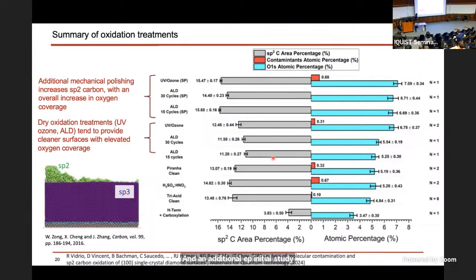And in particular, mechanical polishing, which sometimes you need to do to make your diamond smooth enough for your sensing experiments, can actually increase oxygen coverage through this increase in amorphized carbon, which has been studied in an ab initio study. And then we're also quite excited about these dry oxidation treatments, which seem to provide good oxygen content and low graphitic content.